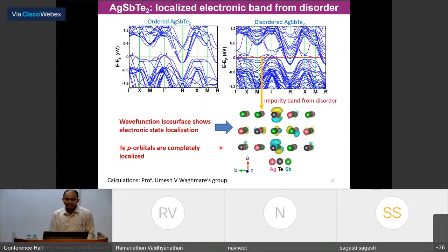So then he showed the electronic structure calculation, the electronic structure of ordered AgSbTe2. It is a semi-metallic structure at 0 Kelvin, so that means it has a nearly flat valence band and a slightly dispersed conduction band, which has a pseudo gap at 0 Kelvin. So now, please see this band. When we disorder the AgSbTe2, we see the localization of electronic states. That is actually what we proposed in the schematic, and these localized states are basically nothing but the tellurium p orbital.